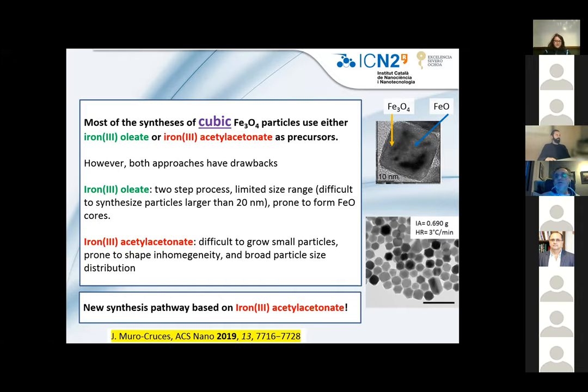But most of the synthesis of cubic nanoparticles has been carried out using either iron oleate or iron acetylacetonate as precursors. However, both systems have drawbacks. When we use iron oleate, this is a two-step process where you first create an iron precursor and then you mix it with oleate. Using this approach, it's difficult to have particles larger than 20 nanometers, and the core is prone to be FeO. I show here an example of a core-shell nanoparticle using iron oleate, where the core is FeO and the shell is Fe3O4. And when you use iron acetylacetonate, it is difficult to grow small particles.